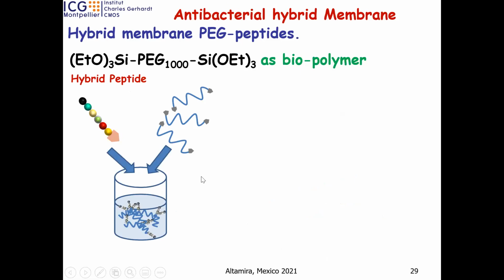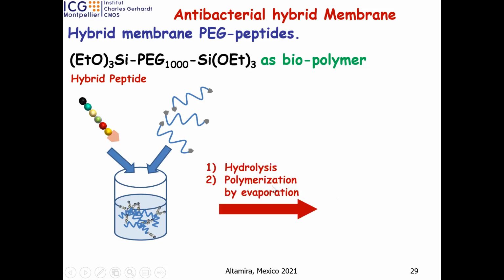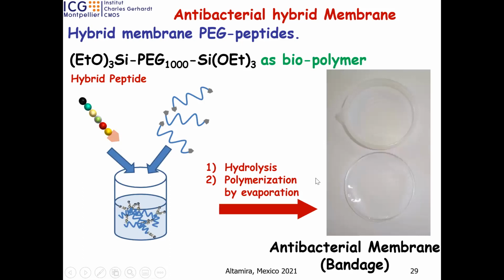Okay, we can prepare an antimicrobial membrane. The idea is we took the same peptide, but we mix it, not with a silica precursor, but with pegylated or silylated PEG. PEG, you know, it's polyethylene glycol, polyethylene oxide, and we have 2 silanes at the end, and we make hydrolysis and polymerization. And by evaporation, we can prepare this type of membrane.